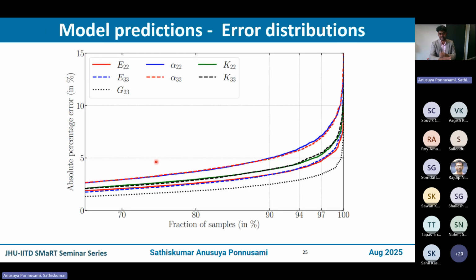Or to give better clarity, this is the error distribution. The APE is plotted as a fraction of samples in your test data. And as you can see, for 90% of the test samples, you get an error that is within 5%, which is really good for engineering design applications. And what is really important is this error, even if you go to the highest error of about 10%, has to be understood in the context of the generality that the model provides. Here, the model is not for one particular fiber matrix combination. It is for an arbitrary fiber matrix combination and for arbitrary material properties. And that is quite important here. So that is what you see here in terms of the results.